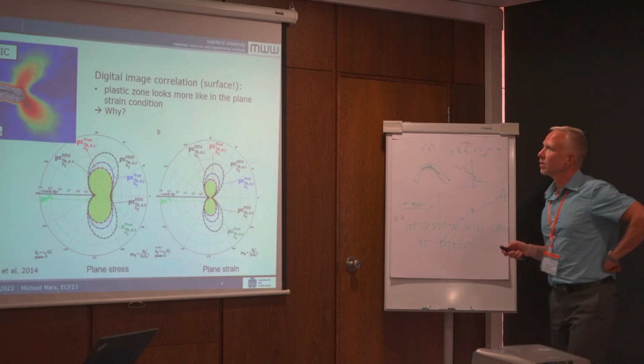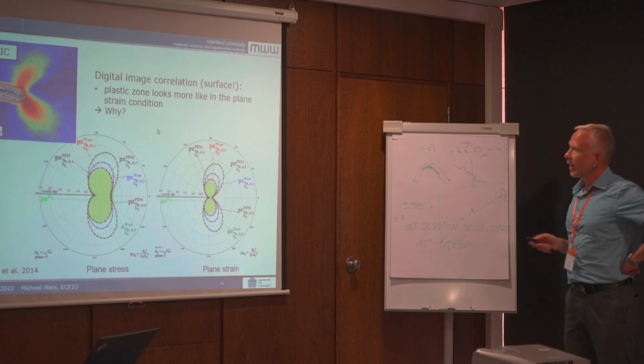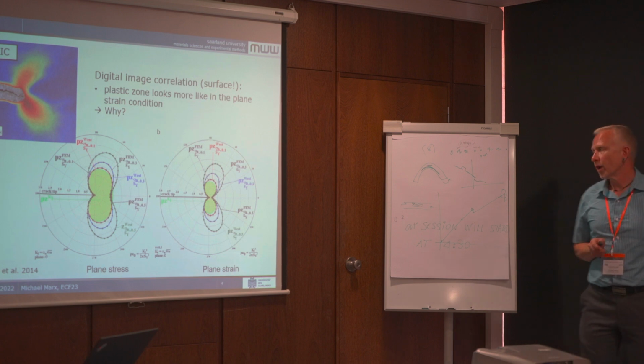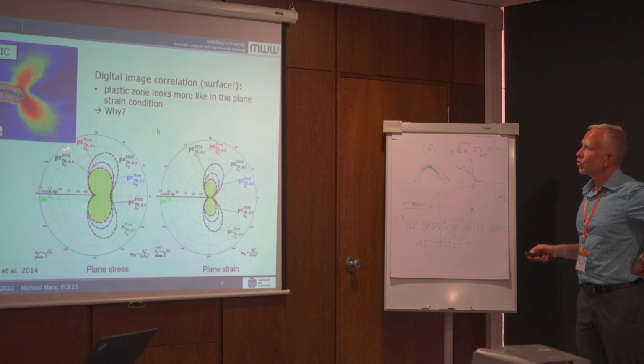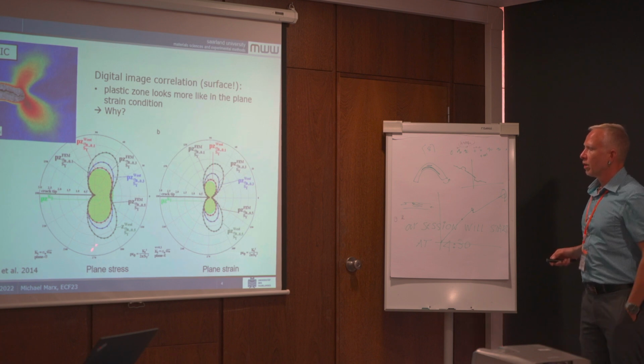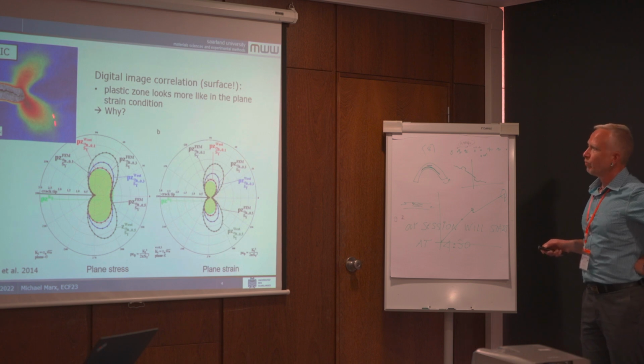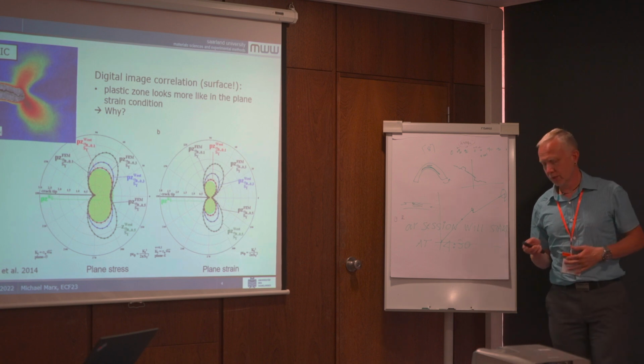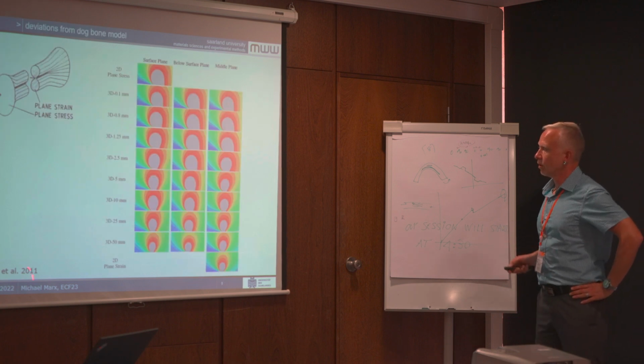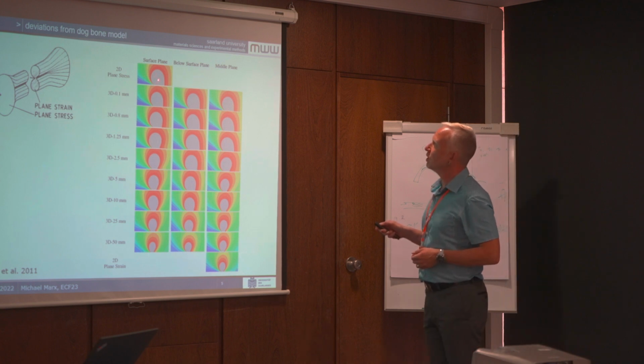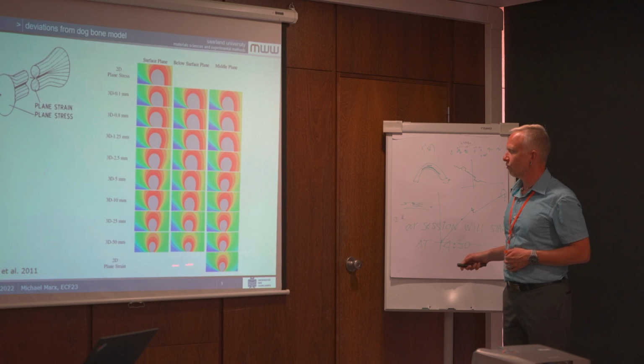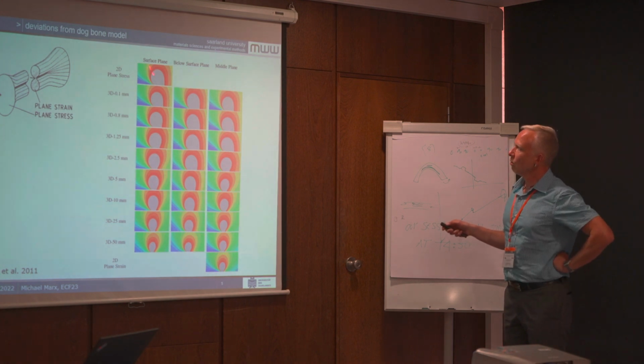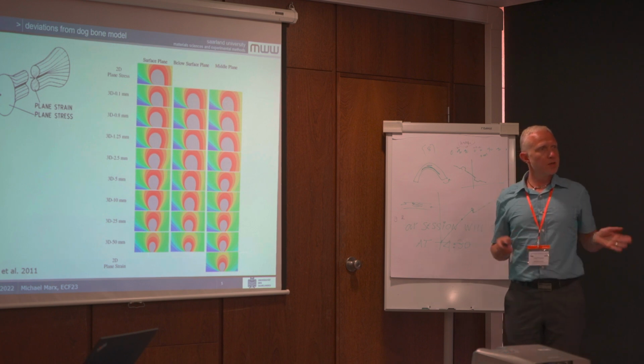What we also did was digital image correlation, which is again on the surface, where we expect to have the plane stress state. If we compare the shape of the plastic zone with the shape we expect from calculations in the literature for plane stress and for plane strain, it doesn't look like plane stress, but a little bit more like plane strain. So it's not what we expected. And if you have a look in the literature, you will find for 2D simulation for plane stress and for plane strain that the plastic zone and the stress distribution are increased at the surface and smaller in the middle of your specimen, as you expect from the model.